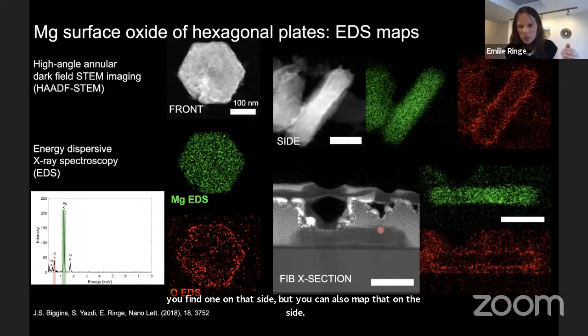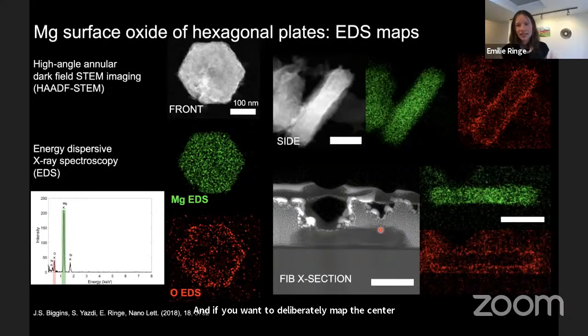And if you want to deliberately map the center, well, you take the particle, you coat it with carbon, then you cut it with a focused ion beam, and now you really have a slice of that particle where you can more accurately measure that coating of oxygen.